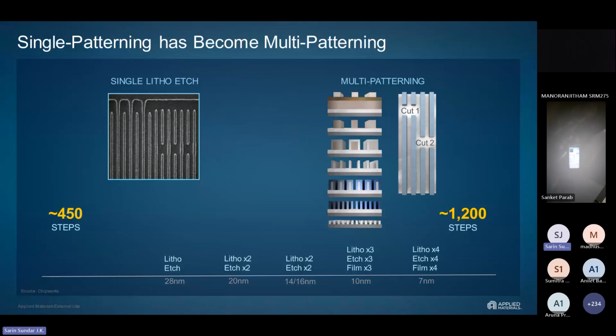Okay, this is a slide, if you are interested, on the steps between 450 to 1,200. Earlier, there are much fewer litho steps. At 28 nanometer, you only do a litho and an etch. Below that, you started doing litho etch, litho etch, litho etch, so litho-etch three times for each pattern. So now it is much more when you go below 7 nanometers. That's how your steps increase.